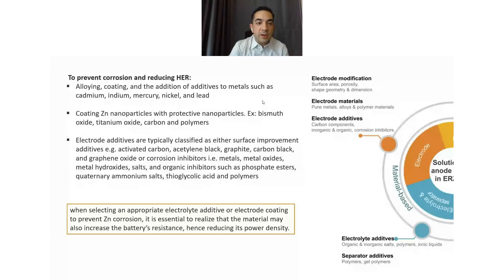Or sometimes you can use corrosion inhibitors as an electrode additive. You can use activated carbon, acetylene black, graphite as an electrode material, or metal oxide, salts, and some organic inhibitor to prevent the corrosion. But once you're selecting an additive for the electrolyte or electrode, you must notice that this material can also increase the battery's resistance and lower the power density. So this might be a point to remember.